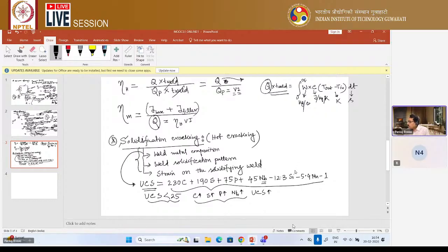Now, which elements help reduce this UCS, or help prevent solidification cracking? Generally silicon and manganese are the elements which help. If the percentage of silicon and manganese is more in your weld composition, then your UCS will be reduced, and the weld solidification cracking will also reduce. This you should keep in mind. This is one aspect. The second aspect is weld solidification pattern.